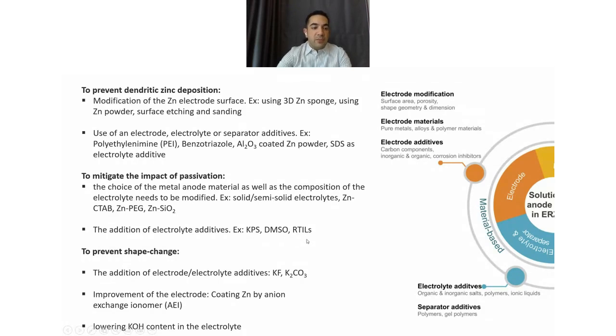The third is the shape change. In order to prevent the shape change, which usually happens during the cycling, it happens as a redistribution of zinc when you discharge and zinc dissolves into the electrolyte. By the time you are going to charge back, it will not deposit at the very same area. So it will sometimes accumulate at some spot and make a deformation to the surface of the anode. So to avoid that, you can use additives for your electrode or electrolyte, like potassium fluoride or potassium carbonate, or you can make some improvement to the electrode, like coating zinc by AEI, or lowering the KOH content in the electrolyte and decreasing the pH can also help in that case.